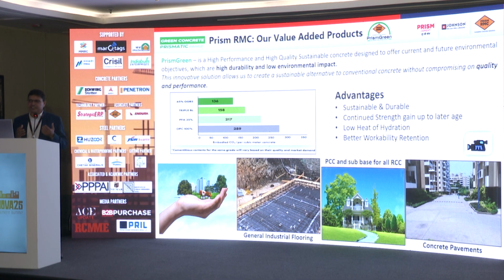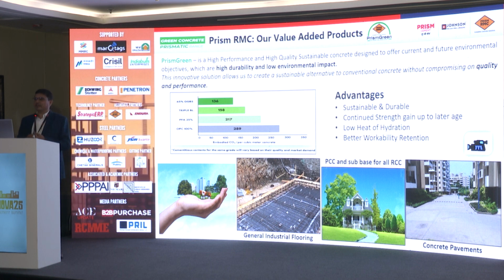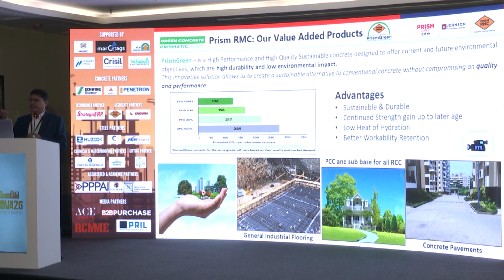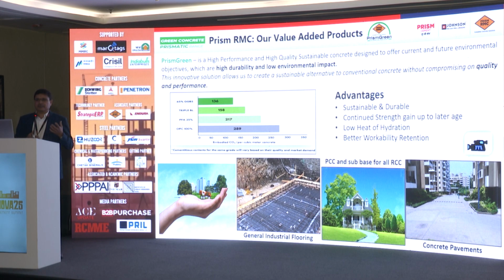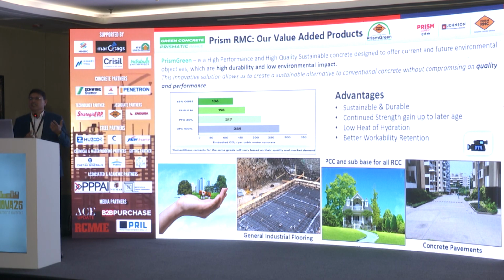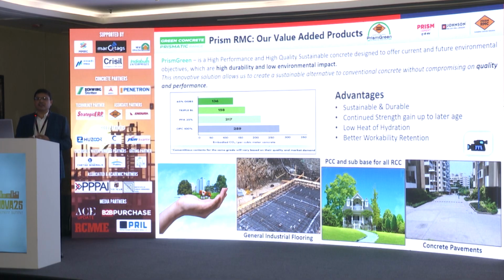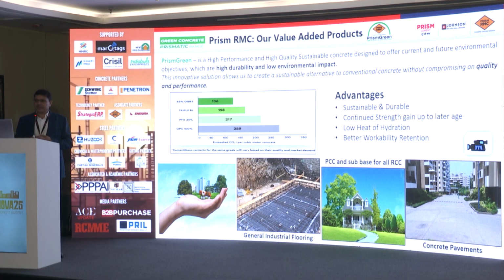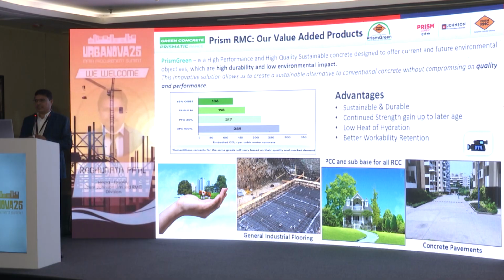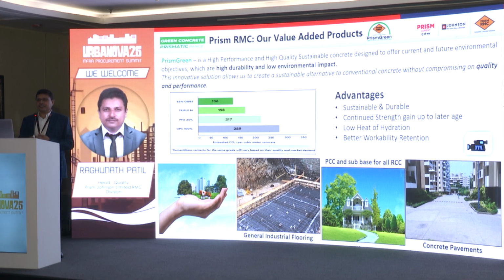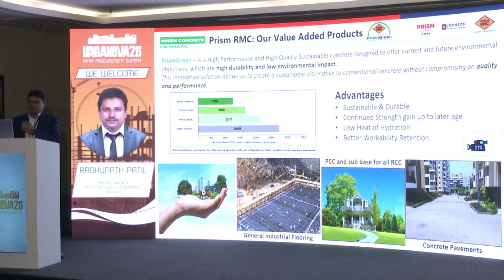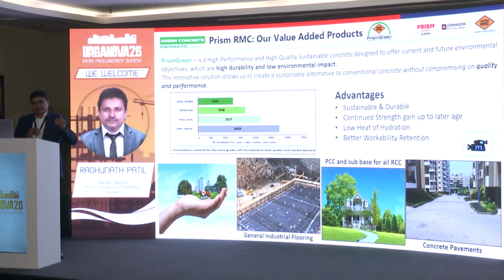Also, in some major cities like Hyderabad and Kolkata, players like Ramky and others have started manufacturing aggregates from construction demolition waste. These are recycled concrete aggregates, and we have tested them. The quality of this manufactured sand is very good and meets the requirements of the Indian standards. But the code has given some limitations. Recycled concrete aggregate can be replaced up to 20% and up to grade M25.